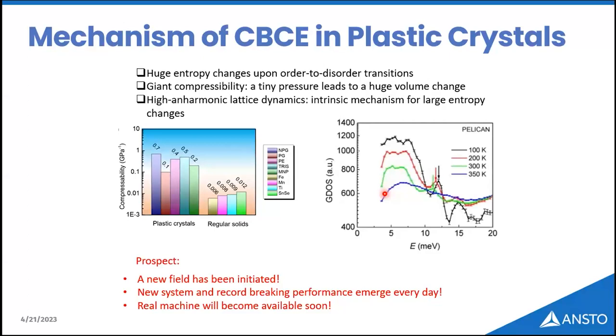we understand the fundamental mechanism for this huge barocaloric effect in this group of plastic crystals. It is due to the intrinsically huge entropy change upon phase transition. It is also due to the highly flexible structure, which gives giant compressibility. Basically, a tiny pressure can lead to a huge volume change. And at the fundamental level, the large entropy change is due to the high anharmonic lattice dynamics. So this study has opened a new field,